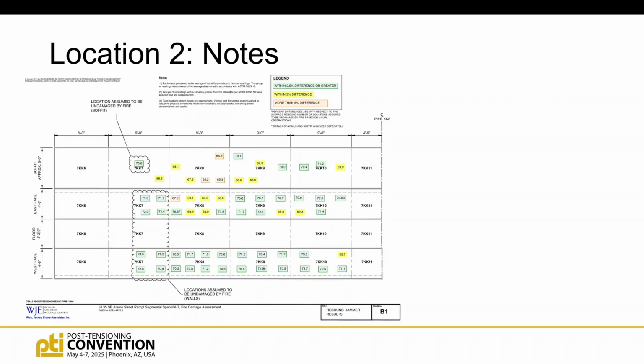Here's our rebound hammer tests. And like I said, we were looking for deviations in the numbers so that would tell us where a hot spot was versus some others. All of these were cast roughly at the same time with the same concrete mix, so we weren't worried about variations in concrete mixes. But we didn't get a big deviation using the rebound hammer.